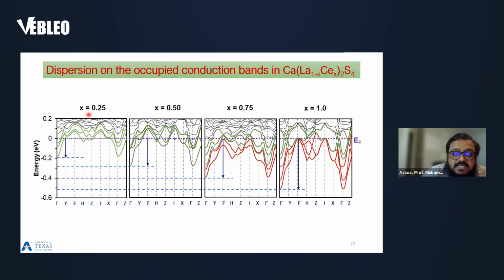What happens as we start increasing the cerium or 4f electron concentration at the higher values of x, there are fully occupied bands. The red bands are a portion of the bottom of the conduction band. These red bands are fully occupied, green bands are partially occupied, and the black bands are unoccupied. What we see with x equals 0.75 and x equals 1 is that fully occupied, partially occupied, and unoccupied bands create a continuum without any gap in these two. Hence, they show metal-like behavior.